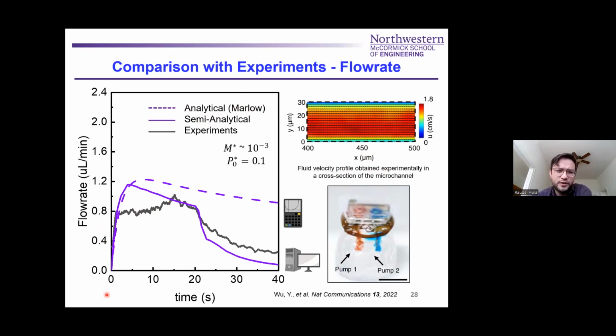So what's interesting is that first, with the semi-analytical model, we can see that we end up over-predicting the behavior a little bit here. And I think this might be an issue with channel compliance. If we have a very high, accelerated flow rate at the very beginning, we might end up expanding the channels.